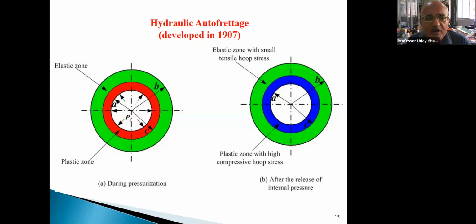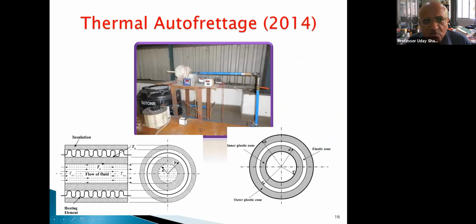So what happens in this one is that hydraulic autofrettage produces compressive residual stresses inside, and outside we may have some small amount of tensile residual stresses. So this type of process is also done. We developed here in about 2014, and we have done extensive experiments on thermal autofrettage. Basically in thermal autofrettage, we are producing the same residual stresses by thermal means. Because this point has to be remembered, that here the strengthening is not due to strain hardening, but the main strengthening is due to residual stresses. Like we have even shot peening, where we inject a lot of balls onto the surface just to induce compressive residual stresses.